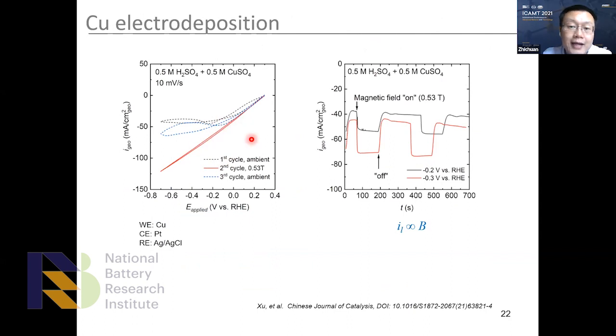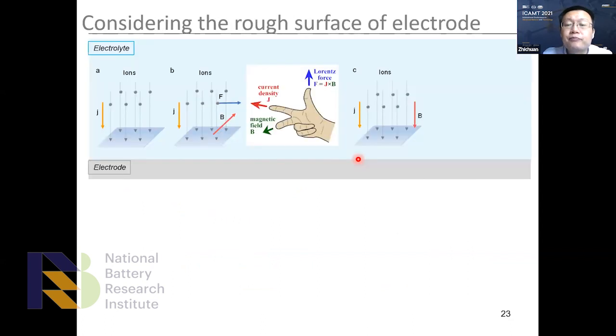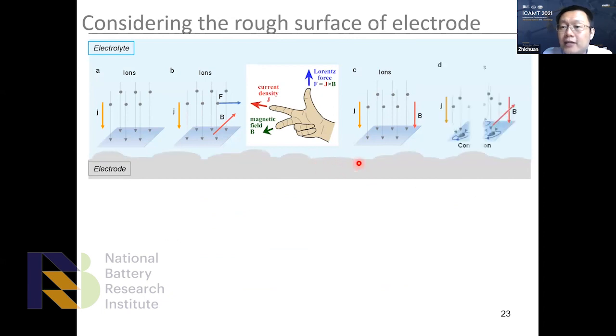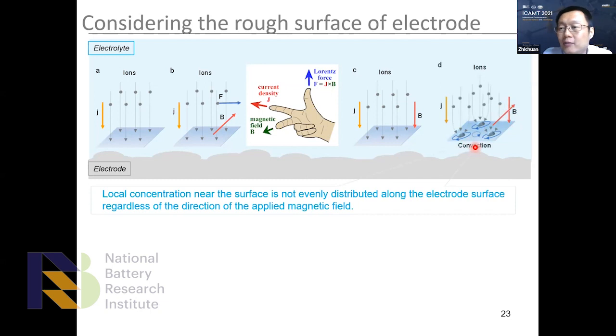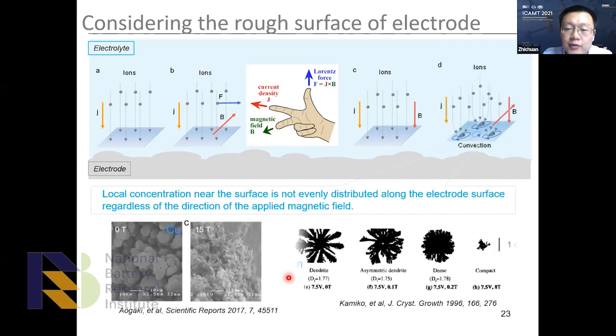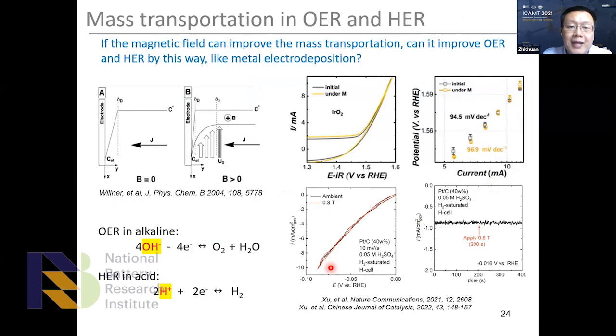Lorentz force will work on that. We can see that when we have a magnetic field on, the limiting current indeed increases, right? And again, we emphasize that the direction does not matter, because the real electrode surface is not very rough. So no matter which direction we apply, we always get a convection caused by Lorentz force. This has been widely observed for metal electrodeposition. They can observe the dendrite formation, etc. This is because of the magnetic field.